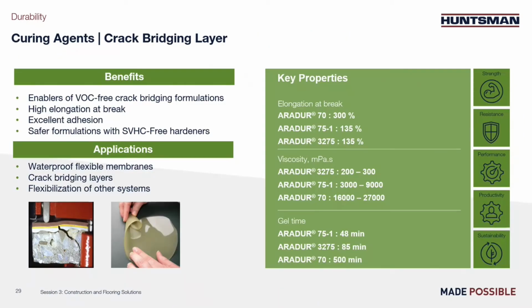Here, another application called crack bridging layer. So often when people think about epoxy, they assume it will be very hard, but actually it does not always have to be that way, to be hard. So the few hardeners presented here have been designed in view of high elongation at break. With these systems, it is then possible to reach up to 300% elongation at break, a bit like a rubber.